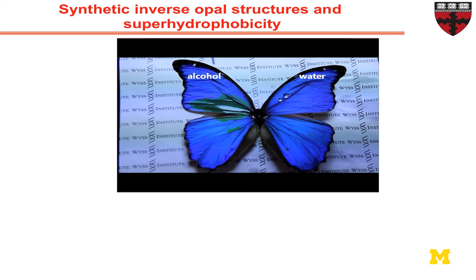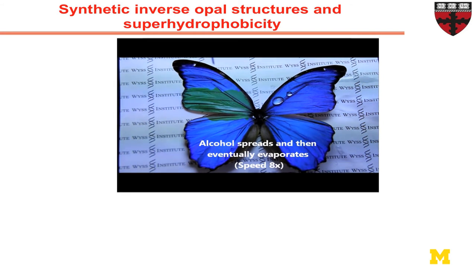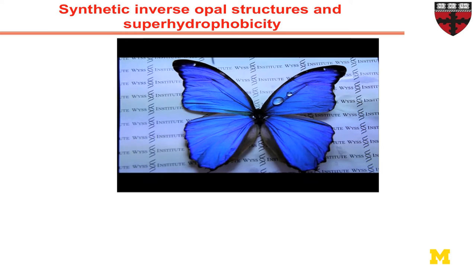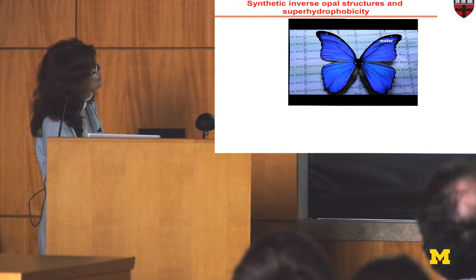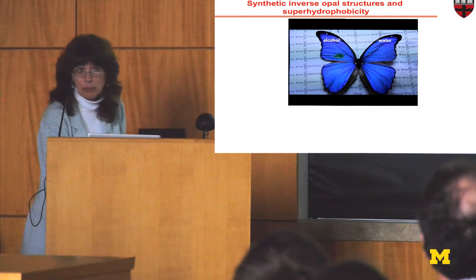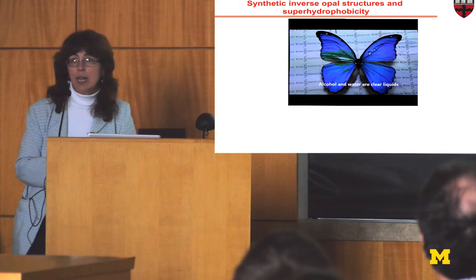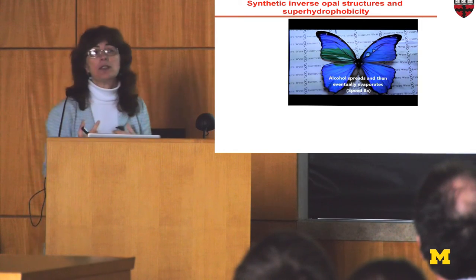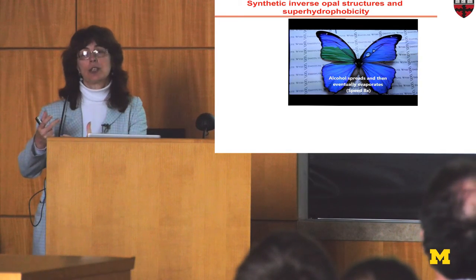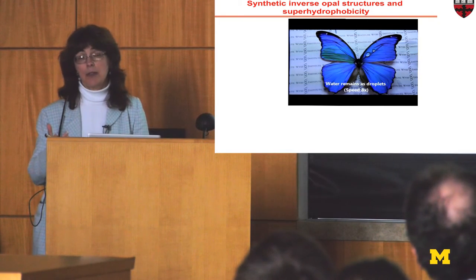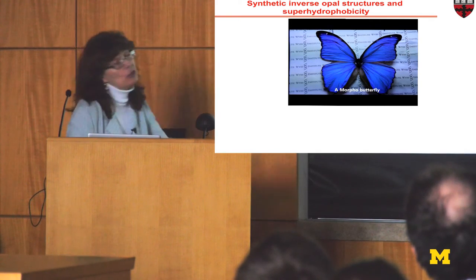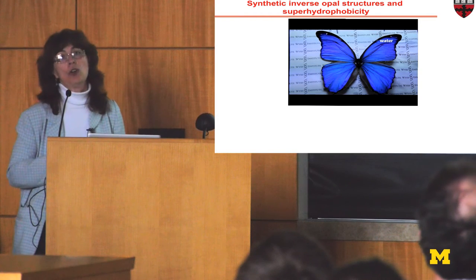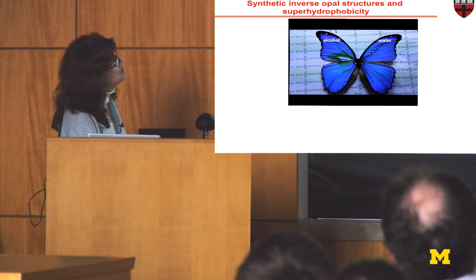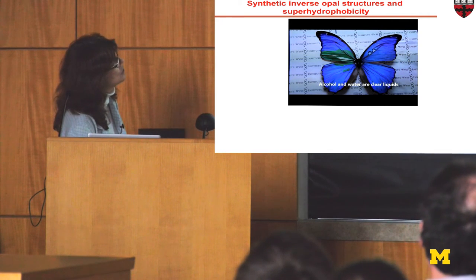So yes, we now can make defect-free inverse colloidal structures. So let's go back to superhydrophobicity, and the butterfly probably is the best example to show here. So here is the superhydrophobic wing of the butterfly. Water droplets run away. If I put alcohol on these surfaces, they don't run away because it's now infiltrating the surface. But since it's structural color, as it infiltrates the surface, the refractive index contrast between the structure and the liquid that is inside goes down, and therefore the color is gone. So the only color you see is actually the underlying color of the pigment below the wing. But it's reversible: the moment the alcohol evaporates, it goes back to its original color.